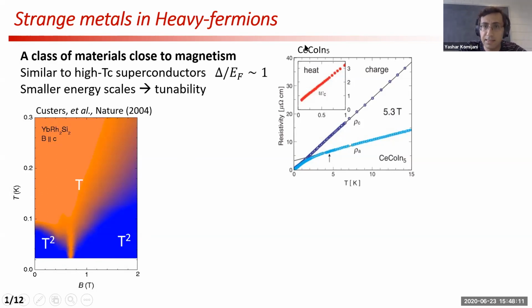This is another example, cerium cobalt indium 5, which is critical at ambient pressure, and the resistivity shows this linear-in-temperature behavior. The range is not as large as we see in cuprates, but compared to the energy scales of this material, it is still a very large scale. Another signature of this strange metal phase is that typically around this regime, we see Fermi surface reconstructions in the